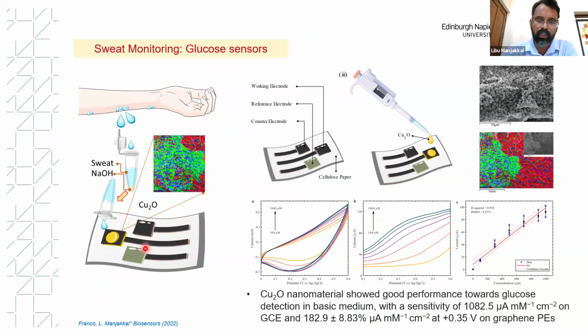And then on top of that, we developed our Cu2O that you can see from here. Then, instead of this, on textile, we demonstrated in this work that we collected the human sweat in an alkaline solution where it was mixed and then dropped on top of the cloth substrate, like a portable sensor.